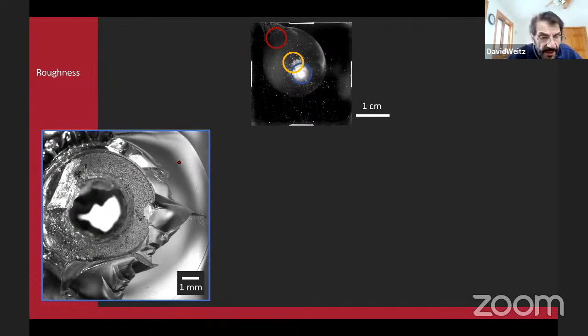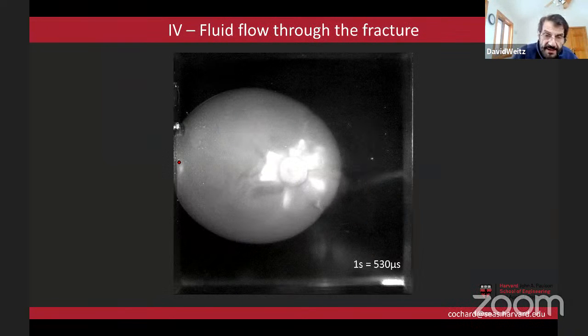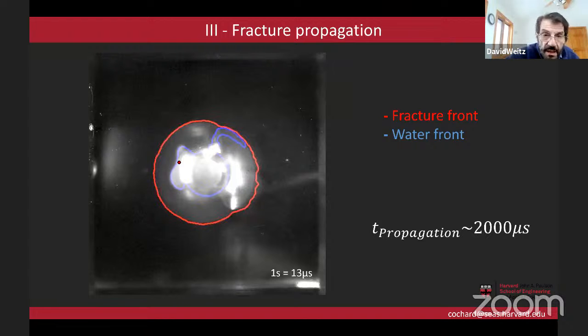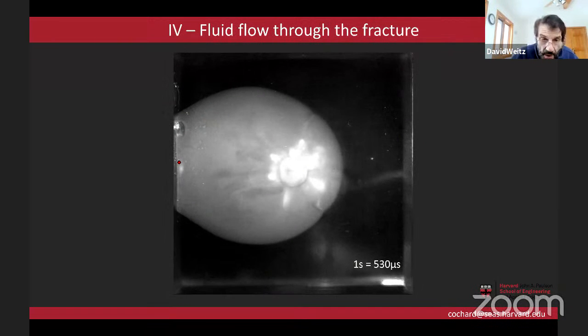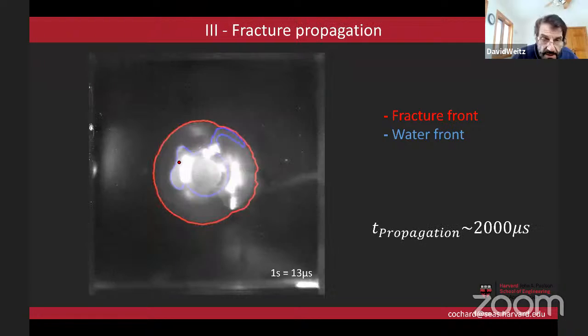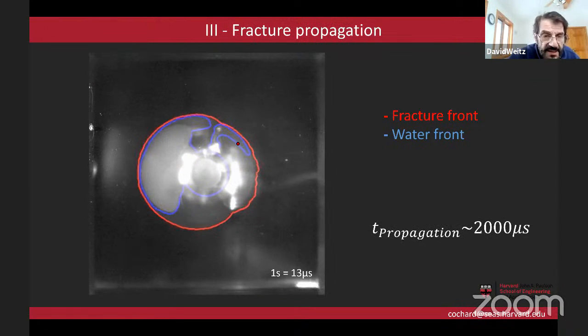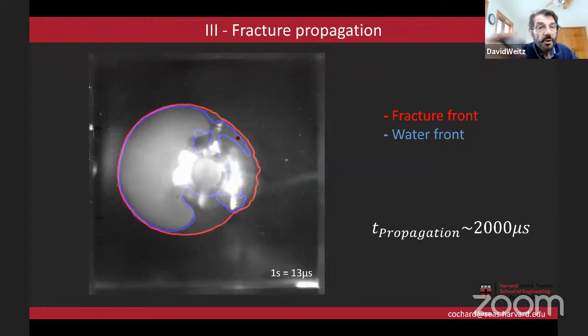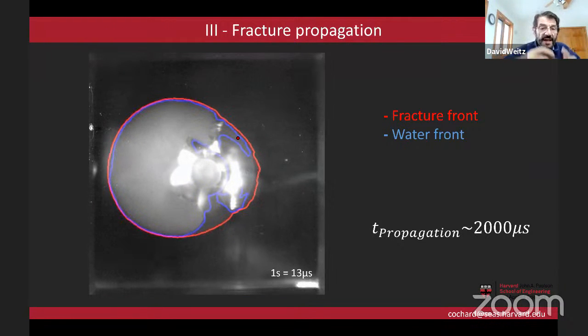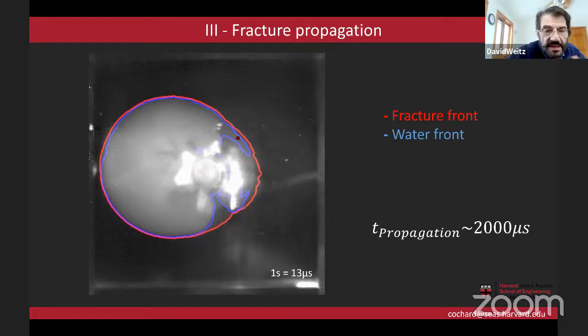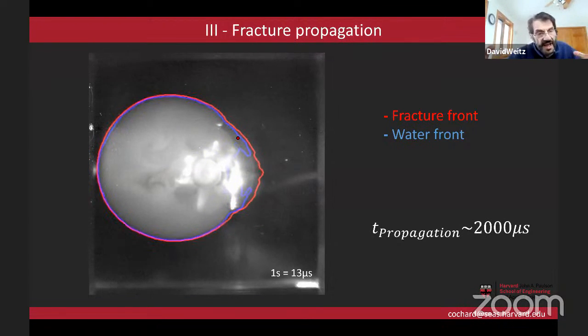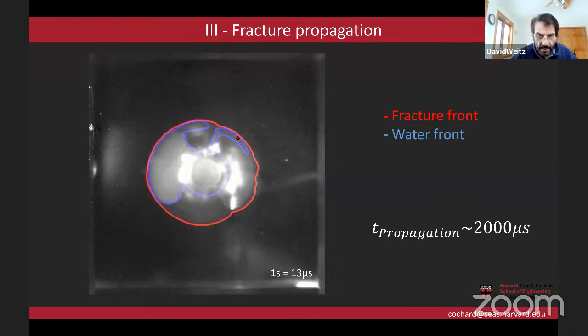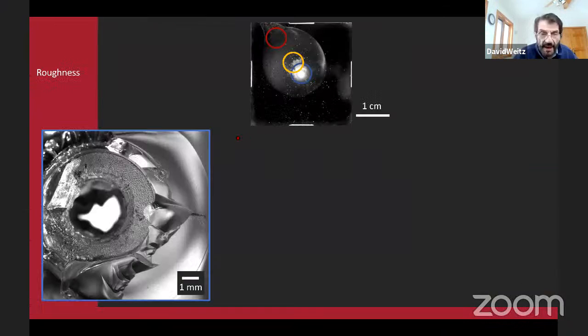We can look at a lot of things. For example, if we go and we look at the behavior, you might ask, in this case, how fast is this crack propagating? What's the speed of the propagation of the crack? It looks like a sort of a stick-slip behavior. The crack moves and then stops, moves and then stops, moves and then stops. It moves ahead, then the water catches up, moves ahead, then the water catches up. So how can we understand what might be happening?